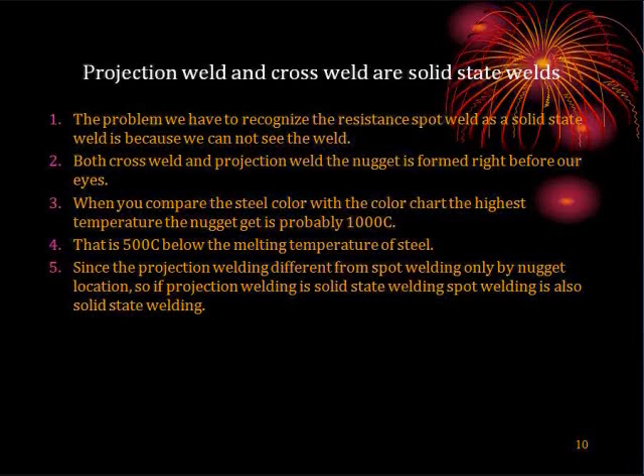Both the cross welding and the projection welding, when you compare the weld nugget itself to the color chart, it's about 900 to 1000 degrees C, which is 500 to 600 degrees C below the melting point of 1500 degrees C. Because of that, those welds have to be solid state welds. They cannot be fusion welds.